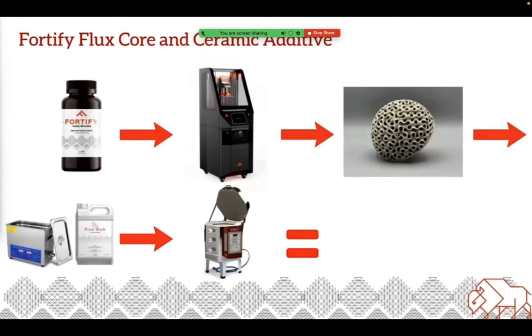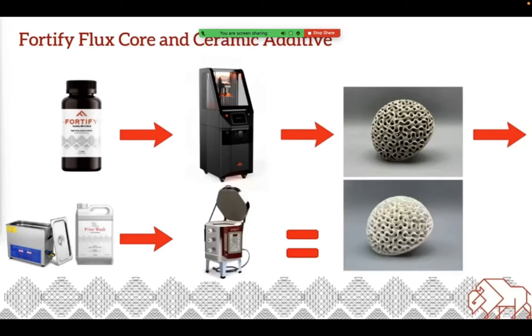However, we then take the part and do a one-step debinding and sintering process. Depending on the material we are printing will determine the amount of time for the sintering process, but generally speaking, it is around a 16 to 24 hour turnaround. During the process, the polymers burn out in a sintering furnace, and the remaining ceramic particles are vitrified to create a true ceramic object. So on this slide, you can see the green objects there on the top right, and then the sintered object is there on the bottom right.